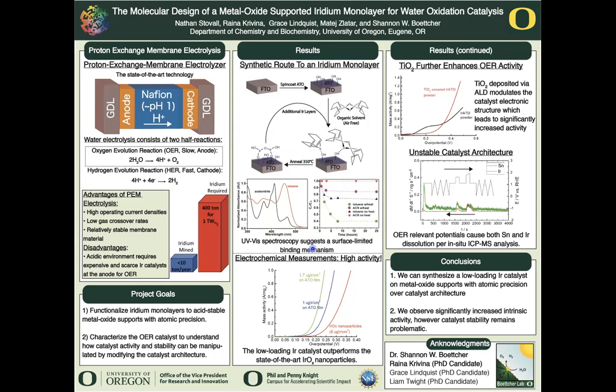But now we've made something, but does this something work? Does the catalyst work? Is it effective? A test that we ran, an electrochemical measurement called cyclic voltammetry, you sweep through a potential range and you measure a current response. And we actually see here that our catalysts, or these two choices on the left, have much more current than their iridium oxide nanoparticle counterpart at much lower voltages, meaning we're losing less energy during the water electrolysis process and therefore making the process cheaper and faster.